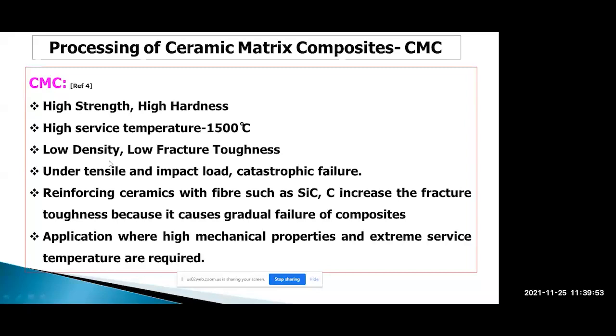They have low density, but the disadvantage is very low fracture toughness. Under impact load, catastrophic failure will occur. So to improve the fracture toughness, these ceramics have to be reinforced, such as with SiC or carbon. This will increase the fracture toughness because it causes gradual failure. We have to convert this catastrophic failure mode to a gradual failure mode by incorporating the reinforcements. Where high mechanical properties must be retained at extreme service temperature, there we use ceramic composites.